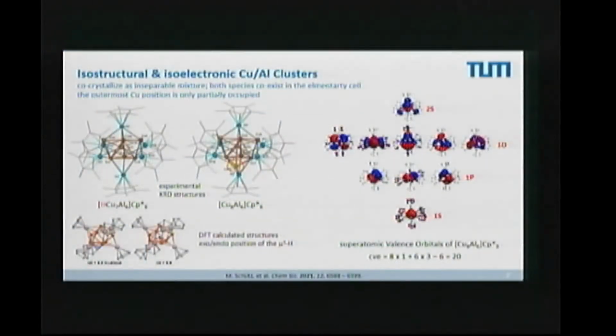So these images here, these plots, are experimental X-ray diffraction data, which we create by fitting the X-ray data to a model where we put the clusters with occupation factors on the elementary cell positions. And then, of course, we go to our theoretical partners, and they do the quantum chemical modeling and the electronic structure characterization. Let's discuss the electronic structure first.